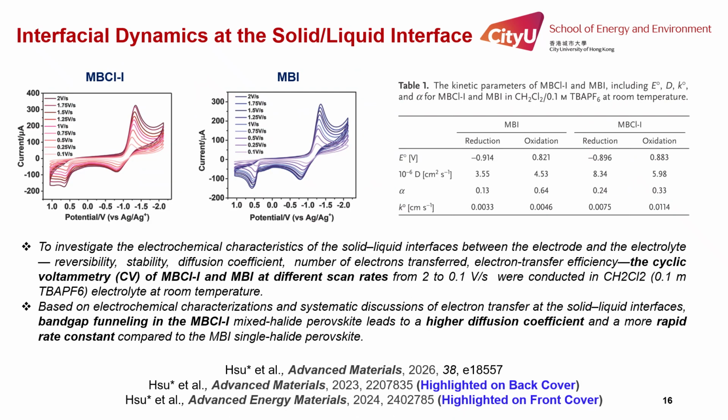To further understand interfacial interactions at the solid-liquid interfaces for bandgap funnel structures, we measure CV at different scan rates for MBCl-I and MBI. And then we demonstrate the MBCl-I with bandgap funnel structure shows higher diffusion coefficient and more rapid rate constant compared to MBI single halide perovskite.